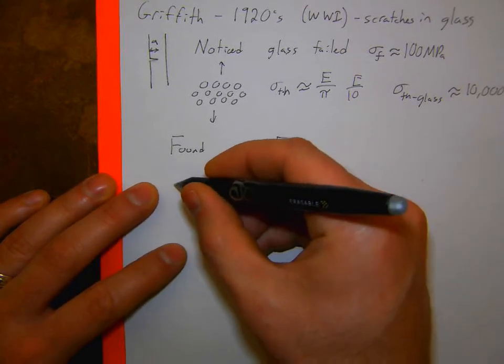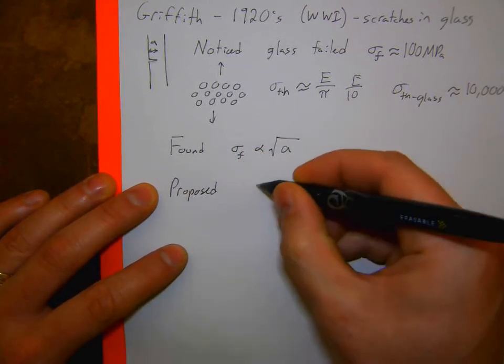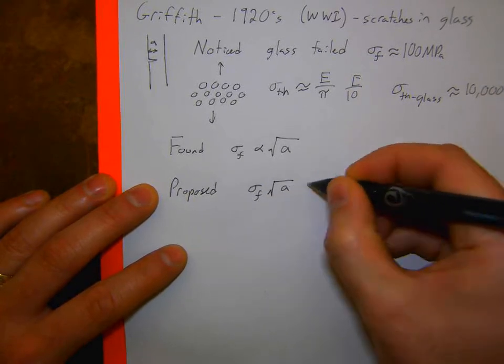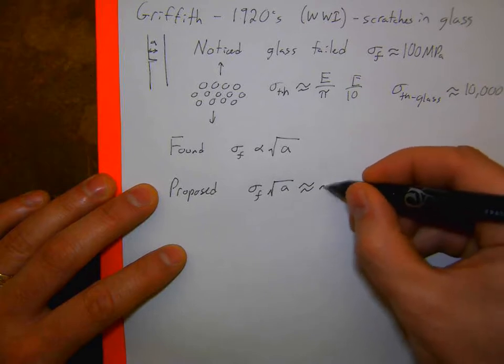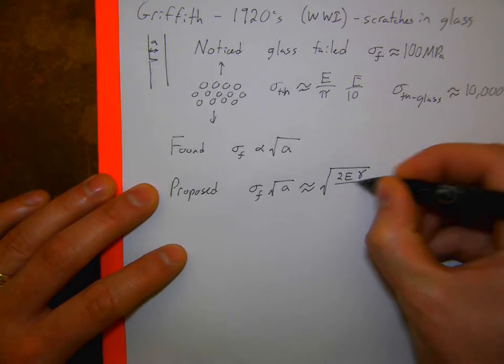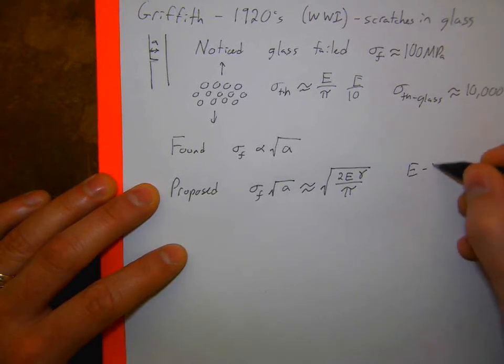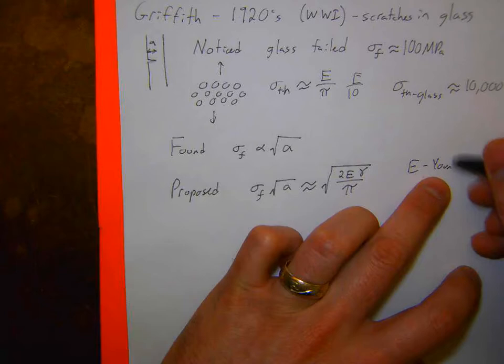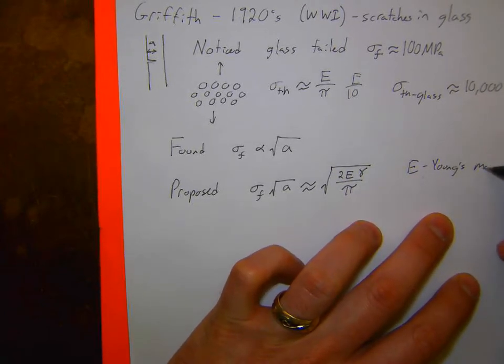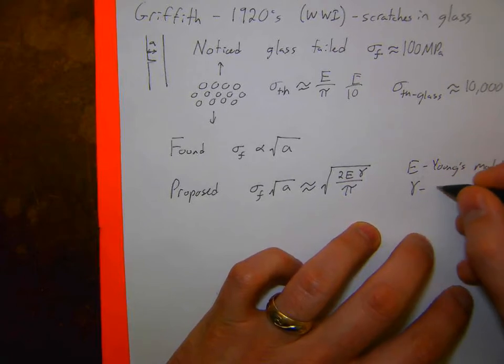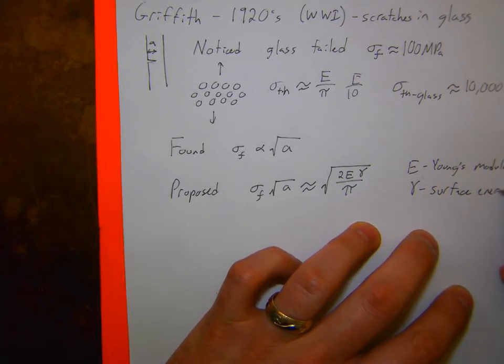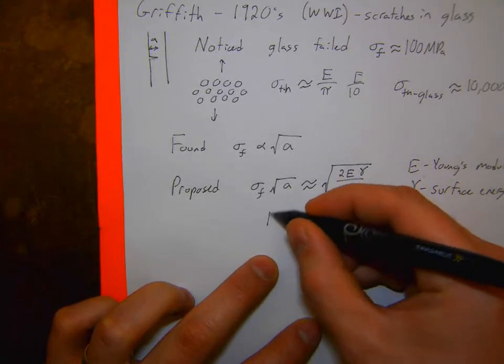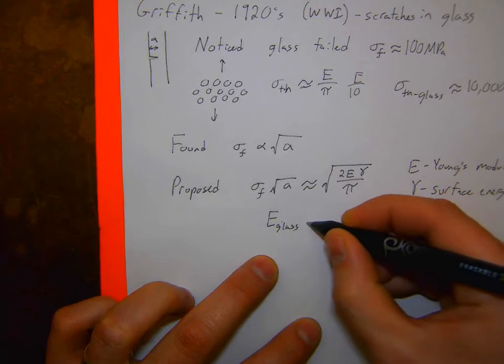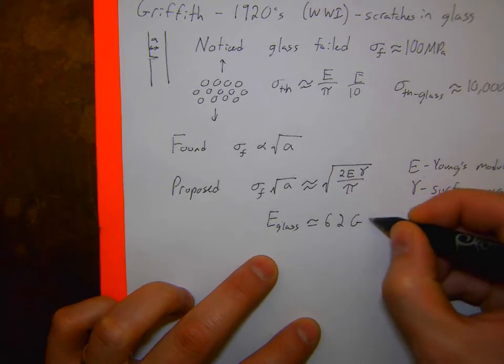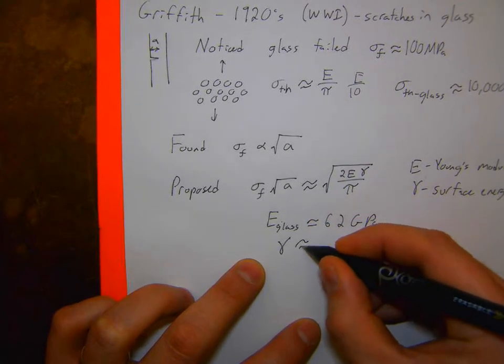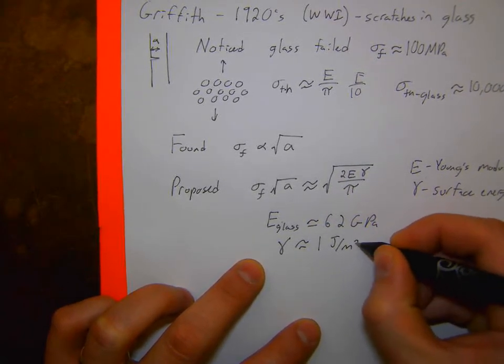So he proposed this relationship, sigma F square root of a is approximately equal to square root of 2E gamma over pi, where E is the Young's modulus, and gamma is a surface energy now. And so that E for glass is around, say, 62 gigapascals, and the surface energy for glass is around 1 joule per meter squared.